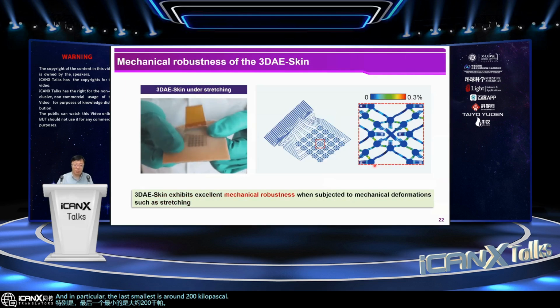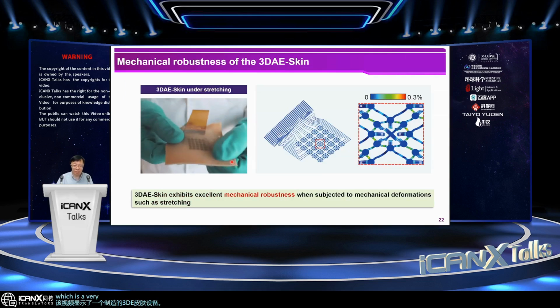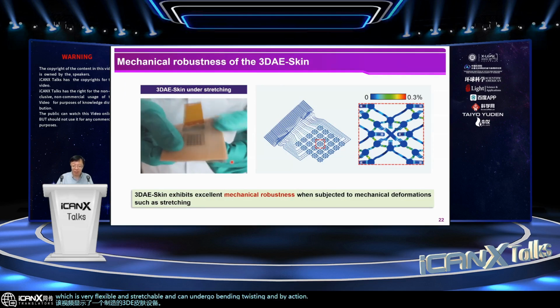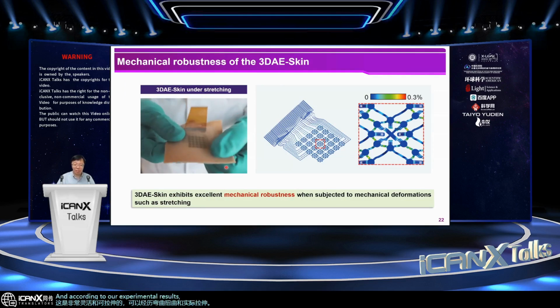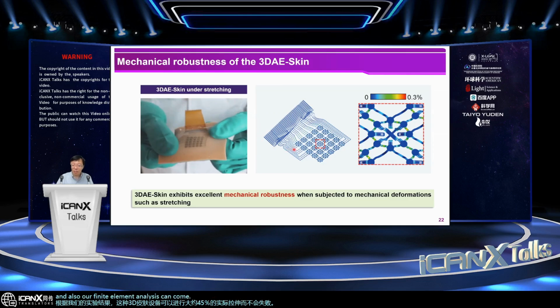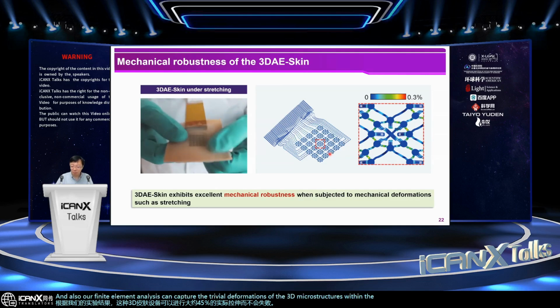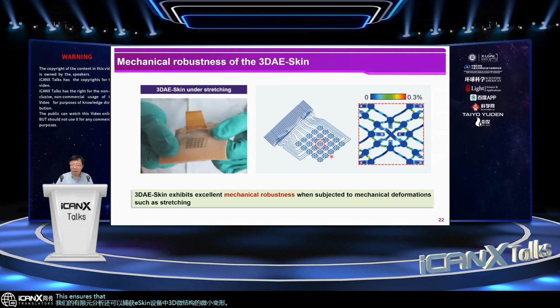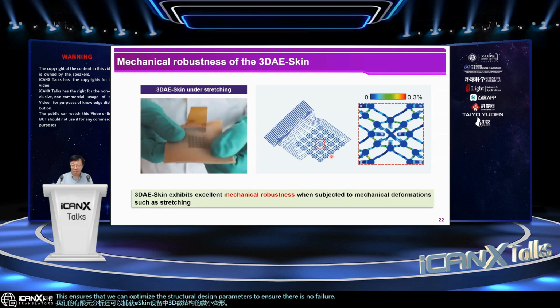Okay, this video shows a fabricated 3D skin device, which is very flexible and stretchable and can undergo bending, twisting, and biaxial stretching. According to our experimental results, this 3D skin device can undergo uniaxial stretching of around 45% without failure. Also, our finite element analysis can capture the trivial deformations of the 3D microstructures within the e-skin device. This ensures that we can optimize the structure design parameters to ensure there is no failure during the deformations.